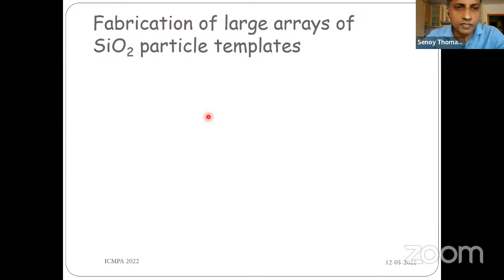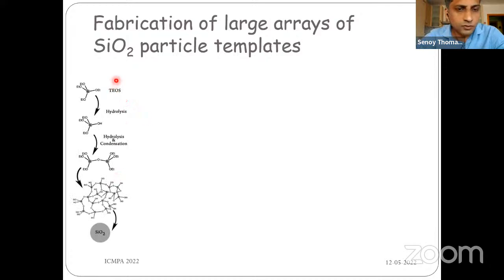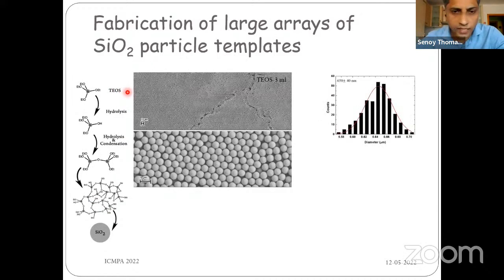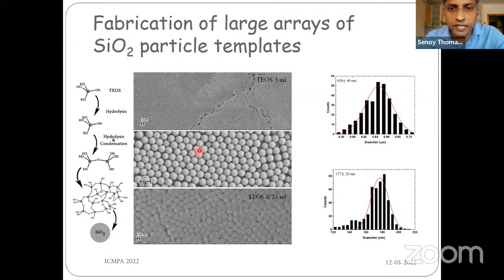For that, we started with preparing a template. Our template is long-range ordered SiO2 nanospheres, self-assembled on the surface of a silicon substrate. For preparing the SiO2 particles, we adopted the so-called Stöber process, which involves the hydrolysis, condensation, and polycondensation of tetraethyl orthosilicate. Depending upon the TEOS concentration, it is possible to realize silica spheres of different diameters. Once the particles are obtained, we self-assemble them on the surface of a silicon substrate, where it is possible to obtain long-range ordering of SiO2 spheres.